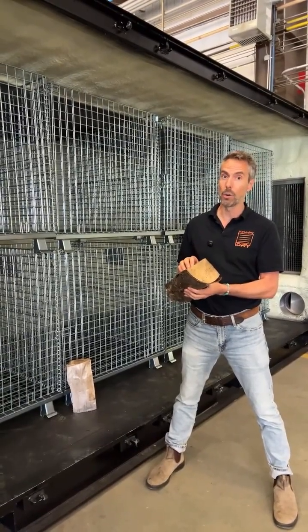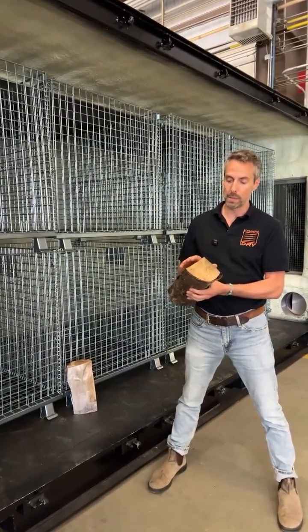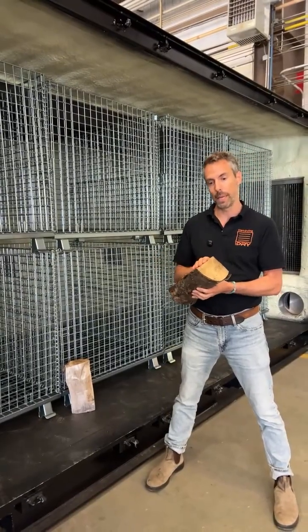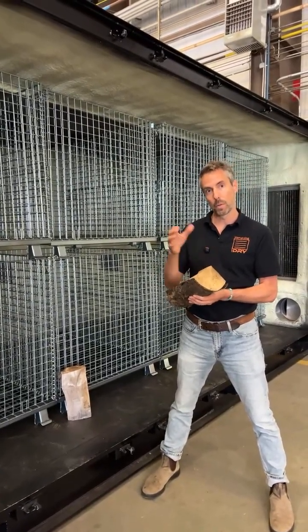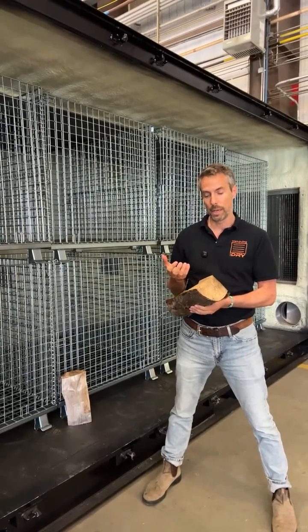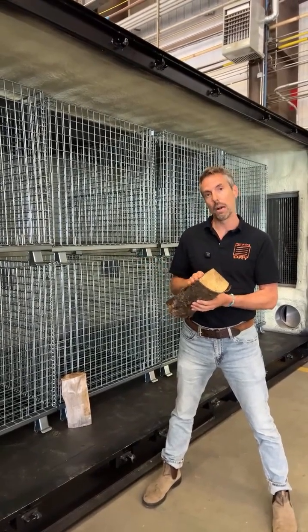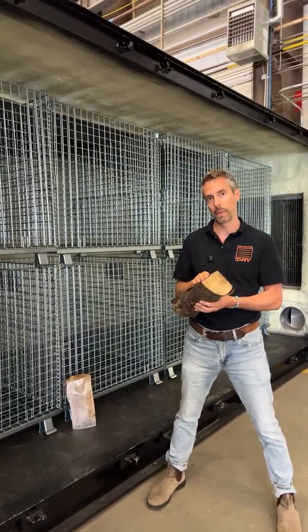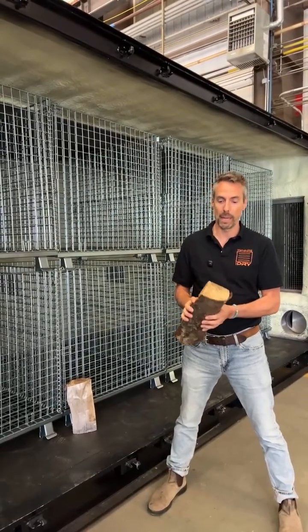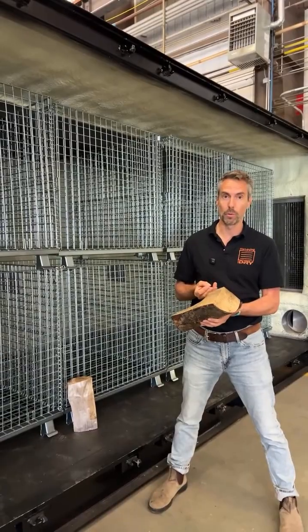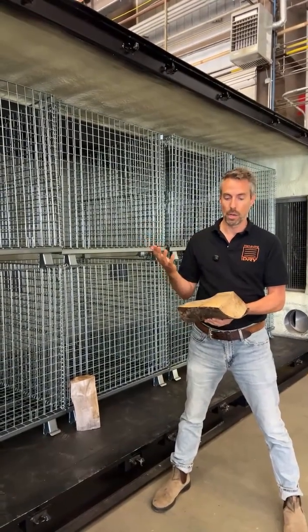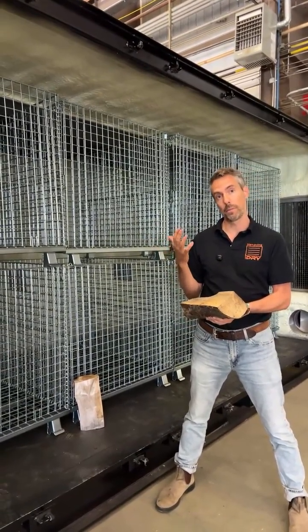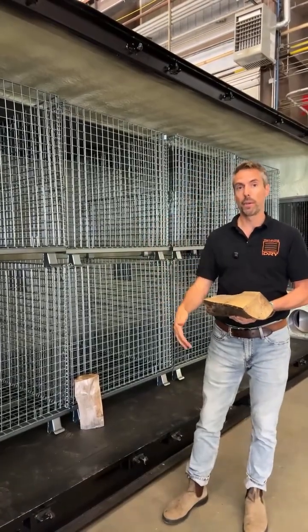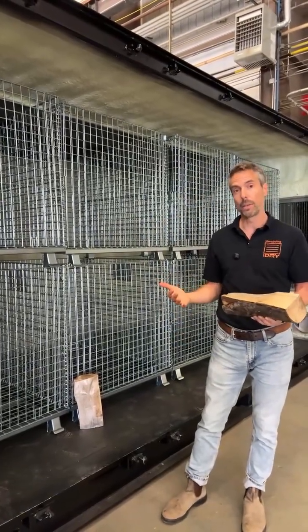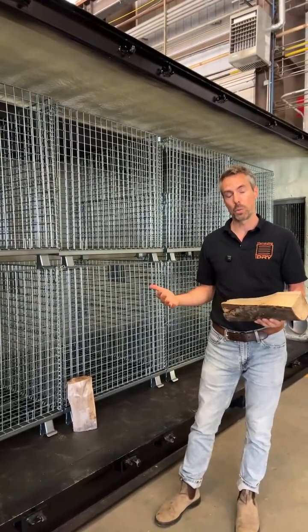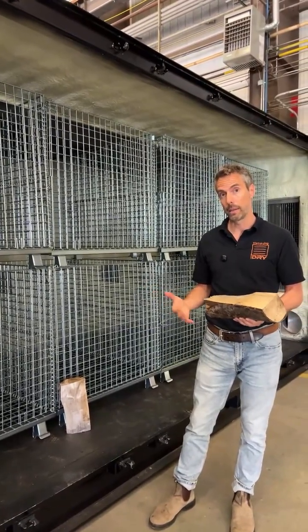If you try to go even faster, then what happens is you just dry the outside shell of this piece, and it reaches below fiber saturation point. So let's say it gets down to 10 or so. It locks up the grain and the fibers of that shell, case hardening this wood, making it really hard for the water to move from the outside of the shell and then out. So yes, we want to dry cordwood as fast as we can, but there's a definite point of diminishing returns where you really shouldn't try to go any faster, or you're just wasting money and fuel.